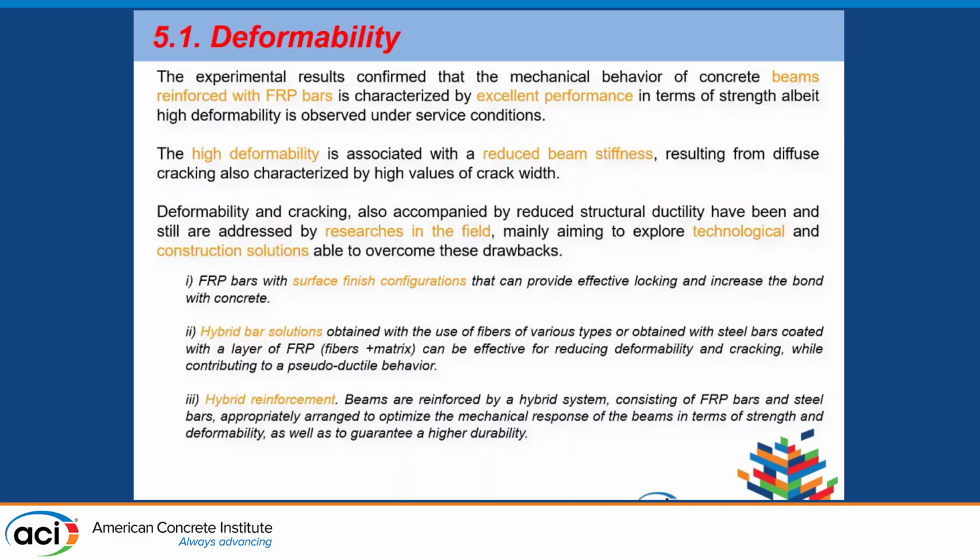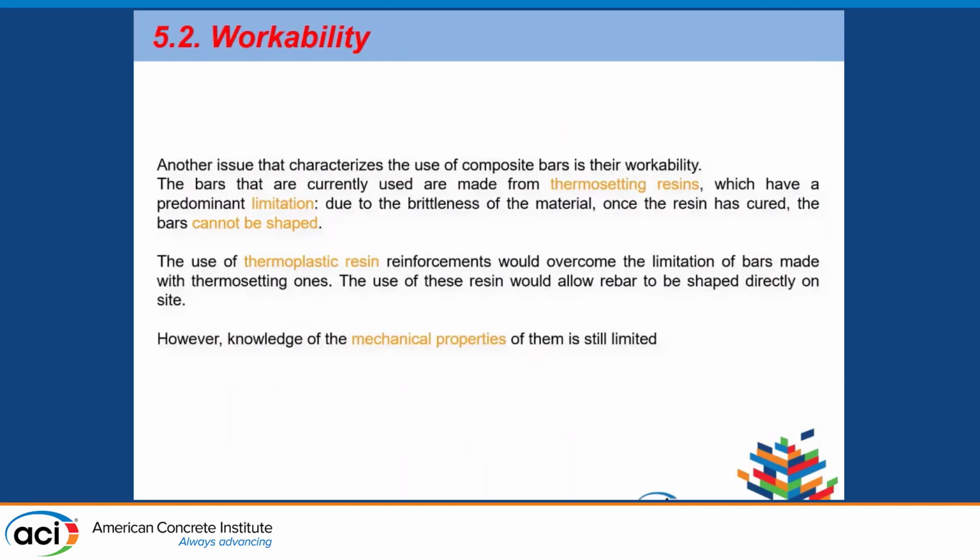And finally, of course, the use of hybrid reinforcement, so the combination of both steel and FRP rebar, which, if properly designed, both in terms of position and reinforcement ratio, can improve the strength and the deformability, as well as guarantee higher durability.